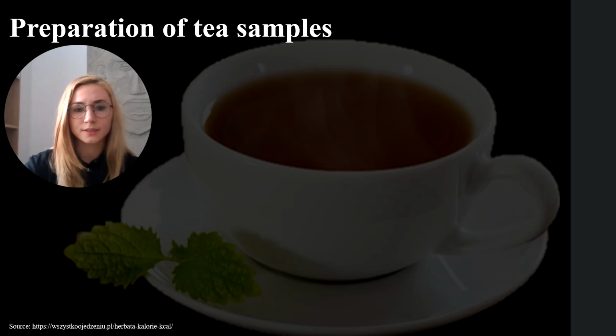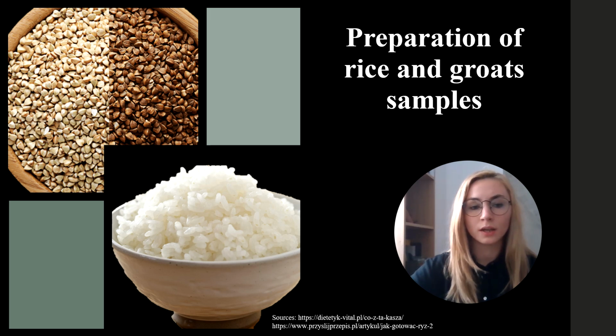The brewing process took place in controlled laboratory conditions using distilled water at the temperature indicated by the manufacturer, and the extraction time was selected as the maximum recommended for a given product. The amount of water used for each single sample was 200 milliliters. After brewing, the tea bag was removed and the resulting infusion was left to cool at room temperature. Rice and groats samples were cooked in 450 milliliters of distilled water, taking into account the maximum cooking time recommended by the manufacturers. After this time, the bags with the cooked product were disposed of, and the remaining liquid was subjected to further analysis.